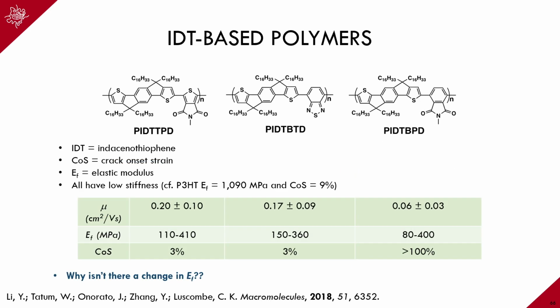So we were convincing ourselves of this, but at the same time in the back of our heads, that argument wasn't necessarily making sense. Because normally, if you have a material that can stretch more easily, that means you have more entanglement, so the chains are entangling. And if it's entangling, your elastic modulus should actually be going up. So you should be getting a stiffer material. But that was not holding true at all. So there is just something about this class of polymers, with this IDT monomer, that generally wasn't making very much sense.